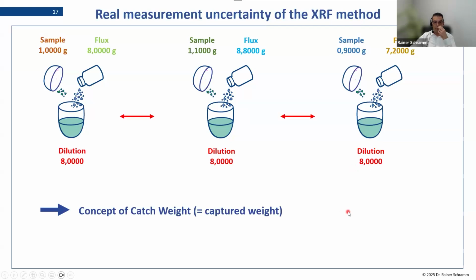So the concept of catch weight means keep your dilution constant, but to make life easier, you could vary your sample weight. You just have to make sure that the flux you weigh is exactly in the ratio of 8 to your sample. Of course, there are limits. You cannot make your crucible too full, because then your mold will be overfilled and you get spillage. Or if you do not have enough material, then you get so-called half moons in your mold. And then, of course, this also makes no sense.